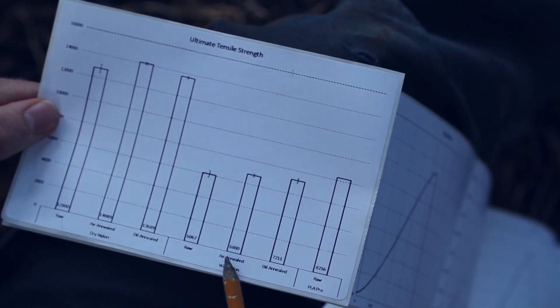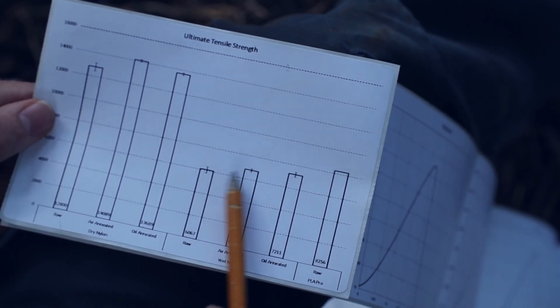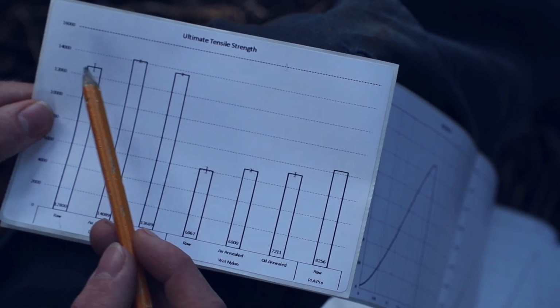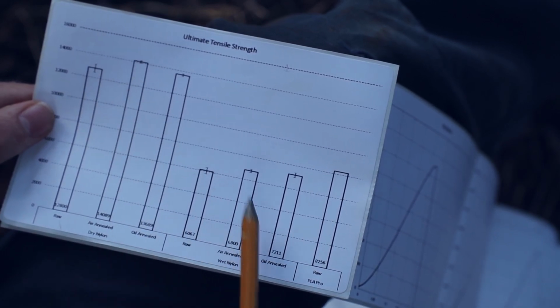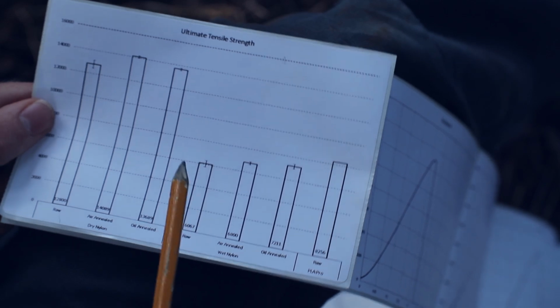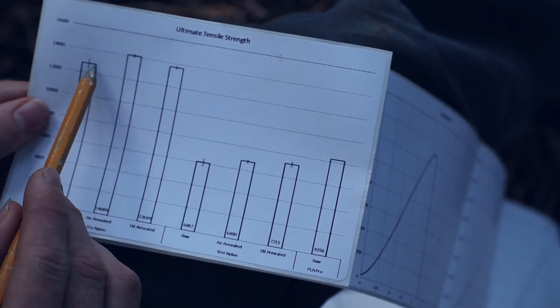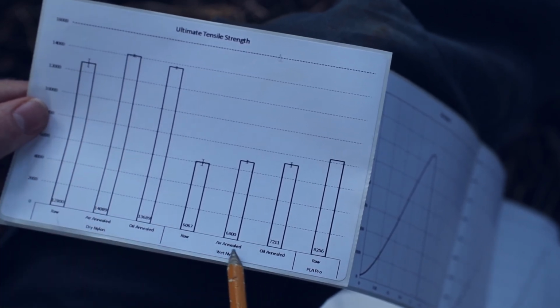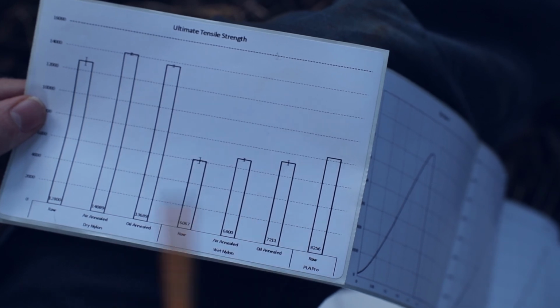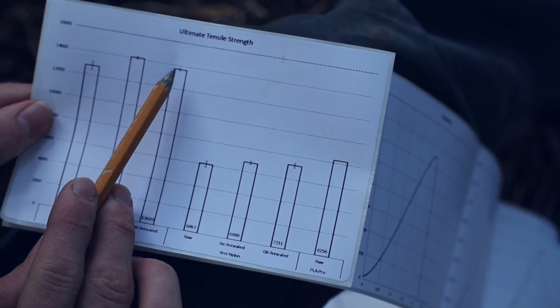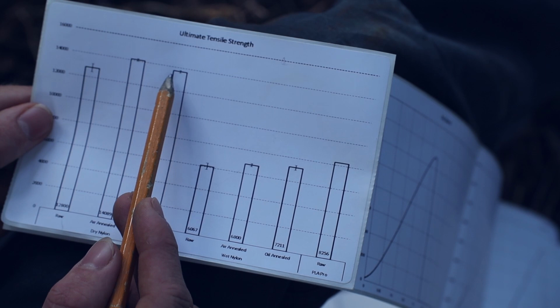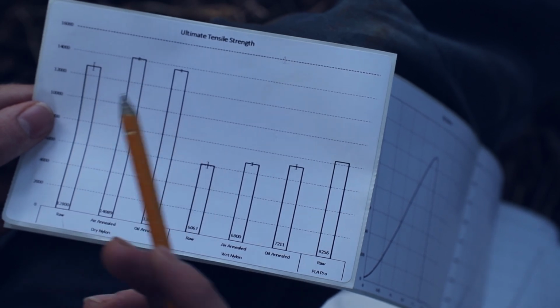The air annealed nylon, once again, is a little bit stronger. It's actually about the same ratio as when it was dry. The annealing is still benefiting us. What's really interesting here is that, unlike when the nylon was dry, the oil annealing is actually stronger than the air annealing. When it was dry, the oil annealing was weaker, which leads me to believe that the oil is making it slightly weaker and softer, just like water.